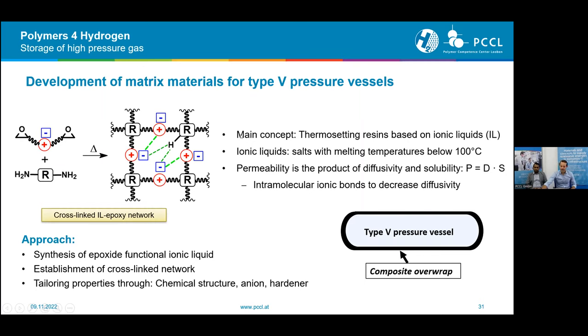And for this, our main concept is once again based on ionic groups. We are using so-called ionic liquids, which are being functionalized to build a thermosetting resin and a cross-linked material. Those ionic liquids are salts that have a melting temperature below 100 degrees Celsius. And we are using so-called room temperature ionic liquids, which have a melting temperature below room temperature. So it is very similar to a regular resin in terms of processing.